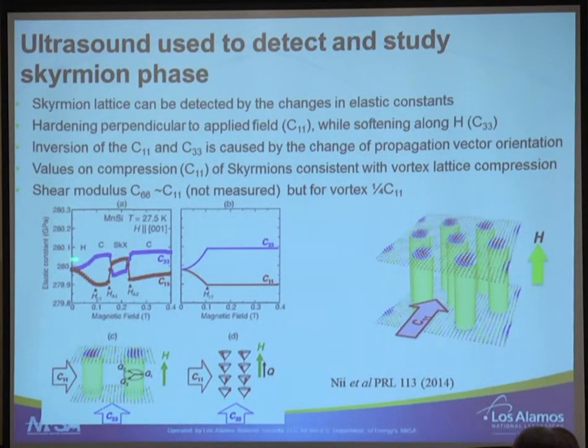Typically, you can see the transition from the helical to the conical phase, and then in the Skyrmion phase you see stiffening or softening depending on which elastic constant you look at. In C11, the one that measures one Skyrmion against the other, you see a stiffening, and then along the field you see softening.